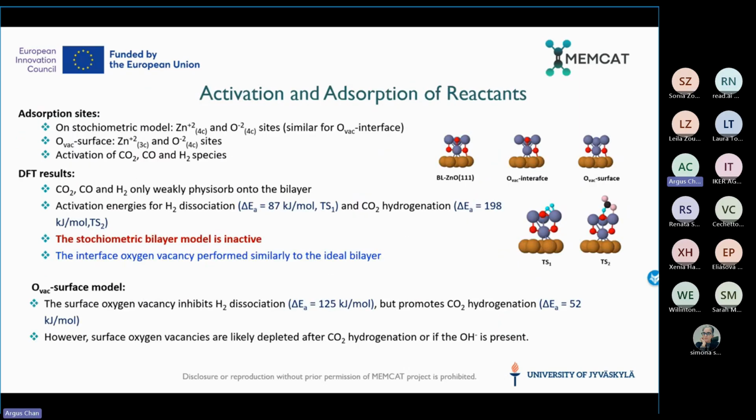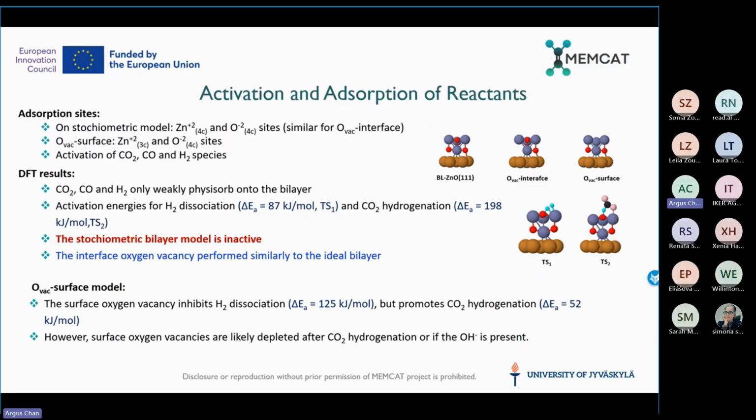With this model, what we see is that if we have the ideal zinc oxide bilayer structure, the reactants only physisorb on the surface, and the activation energy, for example, for CO2 hydrogenation towards formate is rather high. So it looks like this bilayer structure is not very reactive.